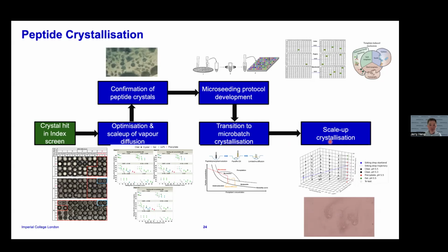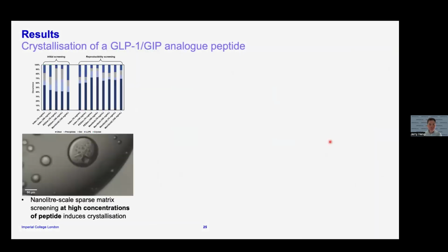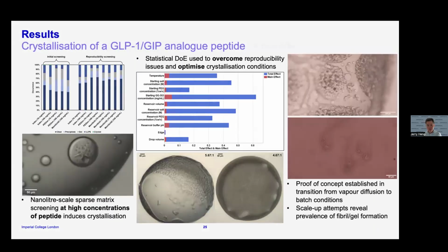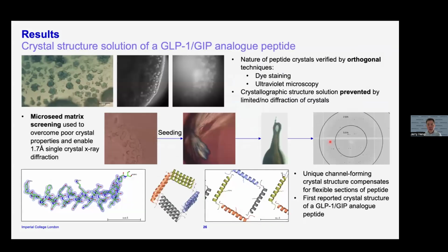What this has resulted in, if I could jump, I think I would jump this slide because I'm starting to run out of time, is the ability through microseeding techniques for us, being Hamish and others, to obtain very, very nice crystals. Very nice in this case means that they do diffract X-rays well. So what the microseeding matrix has been able to achieve was to overcome poor crystal properties.